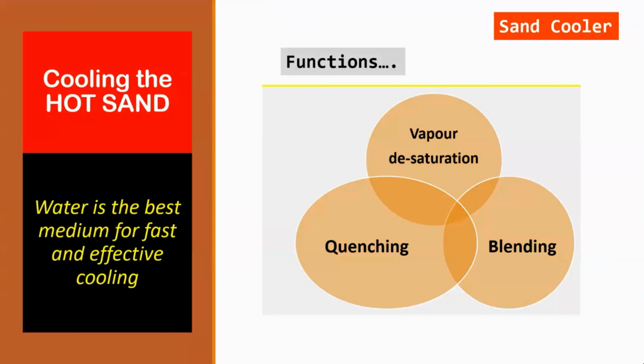And also you have to blow air from the bottom to keep the sand moving about and expose it to as much of the water as possible. Water is the medium for quenching, and then blending is plowing, etc.